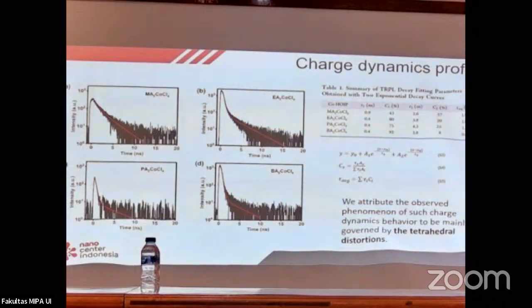And then the main thing that I want to emphasize is that the component of tau one corresponds to the fast component. And then what we found is that the fast component for the MA holds the majority compared to the rest. And then we try to explain it based on the idea that this kind of charge dynamic is mainly governed by the tetrahedral distortion. Because here, for the MA case, the distortion is heavily influenced by the geometric constriction.